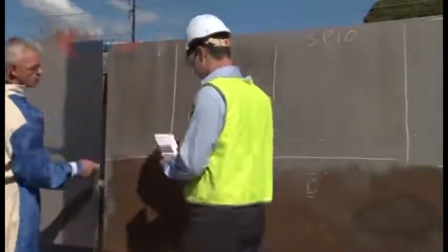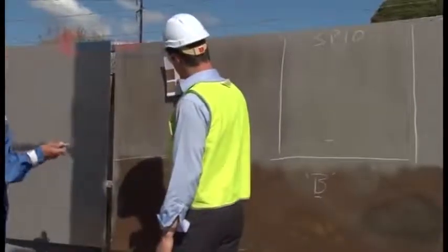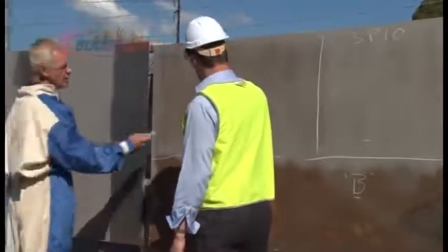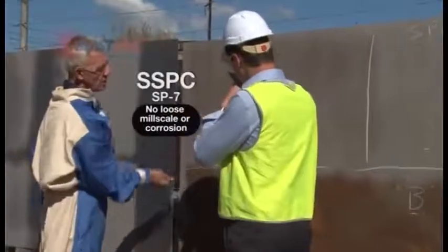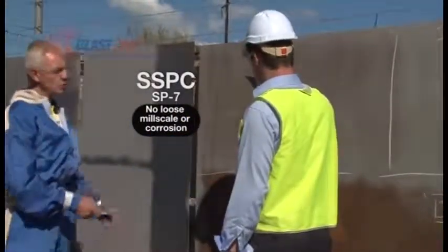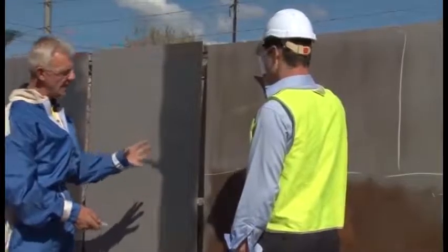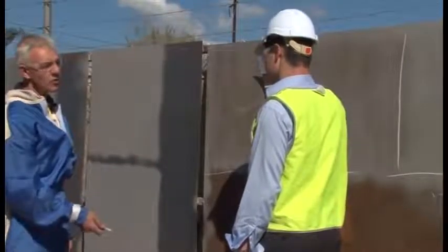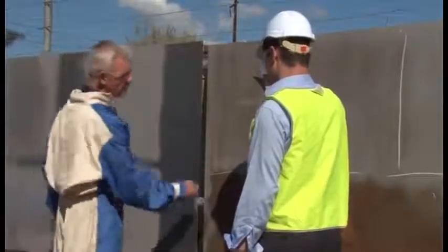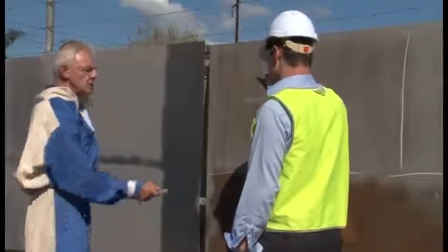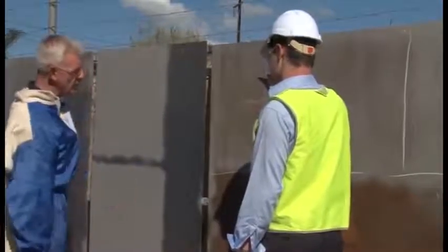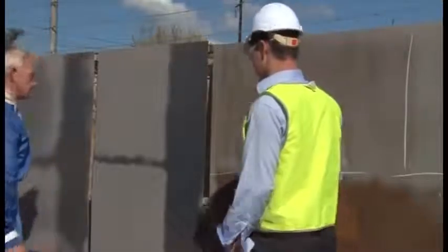So look here on the sweep, look how much cleaner the sweep is on a B grade substrate. Why is it cleaner in conjunction to the standard? Because a B grade substrate will cut cleaner and easier than a D grade will. So consequently, that's why the sweep comes up slightly cleaner. As an inspector, you'll be very happy with a sweep on a B grade substrate.